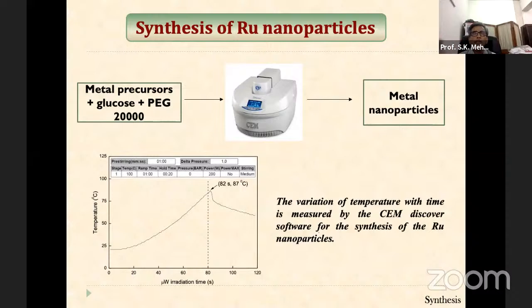There are many examples we have, but I'll give you only one. We have a metal precursor you can take, and for an environmentally friendly system, ruthenium nanoparticle for example, you can use glucose. You have PEG 20,000, and you just put all the material together. You can create the nanoparticles, and you can also see the variation of temperature with time using software, how the temperature varies inside. Very important. The maximum temperature has gone to 87 degrees in 82 seconds. The process is done in very small time, and you can monitor it.